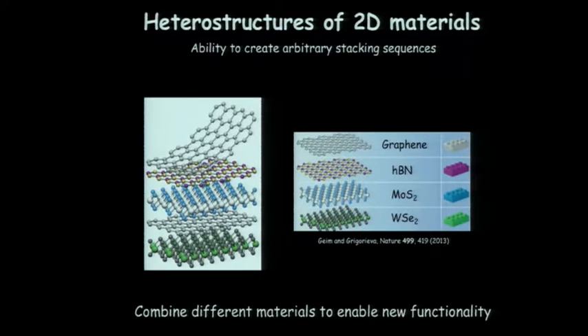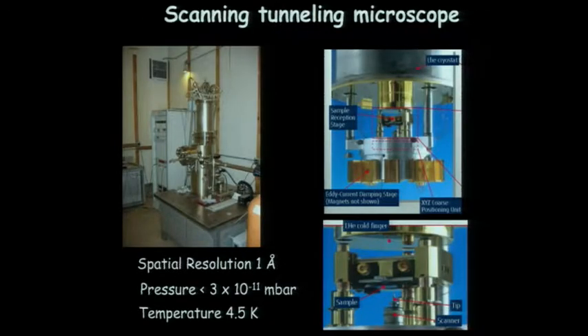And so a lot of that work has been done, thankfully, by Pablo in terms of the fabrication of making these devices, through all their collaborators. And then in my group, what we're mostly interested in doing is probing these materials using scanning tunneling microscopy. So this is the system that we use here. It's a low temperature, so everything I'm going to show you today is done at 4 Kelvin, ultra high vacuum STM. And so the action is happening inside here. We have our tip, and we have our sample up above.